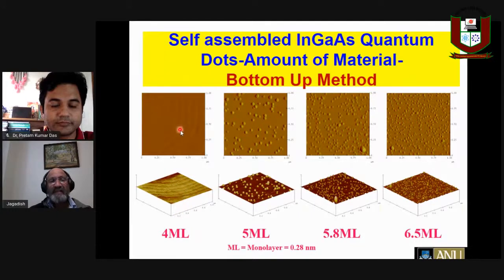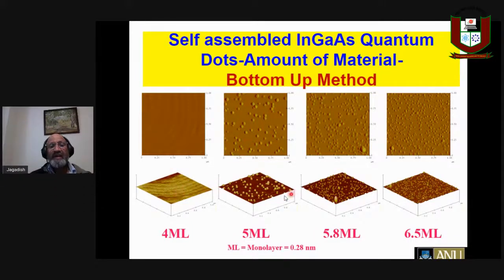You can see the atomic steps on the atomic force microscope image here. If you add a little bit more material, you end up getting 5 monolayers. Suddenly, because of the strain, the surface energy issues come into the picture, and to reduce the surface energy, they start forming into these islands. If you keep depositing a little bit more material, the number of islands increases and the size increases, and beyond a certain point they start becoming clusters, which we want to avoid.